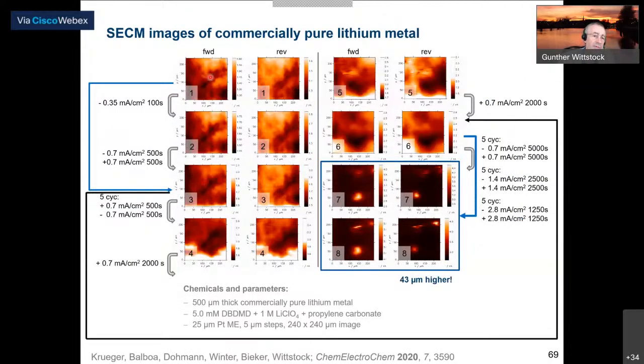And then we could record images in between. So we have an image. We usually record a forward image and a reverse image also as a control measure. And then we challenge the lithium metal electrode with charging, discharging cycles of increasing number and increasing current density. So you see, we started with 0.35 milliamps per square centimeter, and not too much happened. Then we increased the cycle numbers.